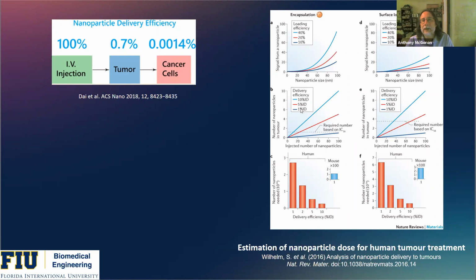These plots show, depending on the delivery efficiency, 1%, 5%, or 10%, how many injected nanoparticles would have to be delivered to reach an IC50 therapeutic response. And so it shows that this could be done with a 1% ID, 1% injected dose reaching the tumor, for the maximum delivery injection of nanoparticles. But if the drug is only surface coated, we would need a 5% injected dose. And here it shows the number of particles that need to be injected versus delivery efficiency.